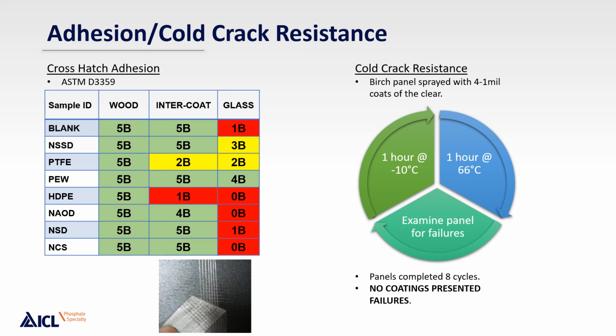And then to create a more strenuous test, adhesion over glass was measured. And here again you can see the difficulty of adhering to glass, but also differentiation between the products. The PEW was the only product that really had a good rating. Again, I think that leads to the lower gloss of the film. But the NSSD and the PTFE also had better results than the blank control.